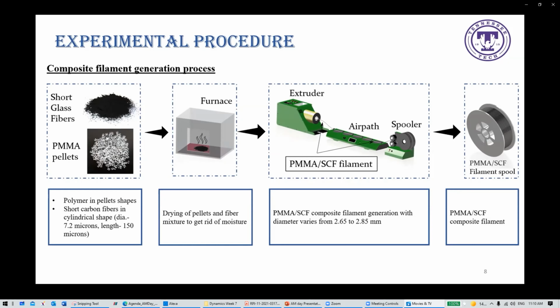So first I took two different materials, short glass fibers and PMMA pellets, for my research. Then I dried them in a furnace for 7 to 8 hours to get rid of the moisture. Then I poured them into the extruder to create a uniform diameter composite filament for the composite denture production, and to use that composite filament inside the 3D printer.